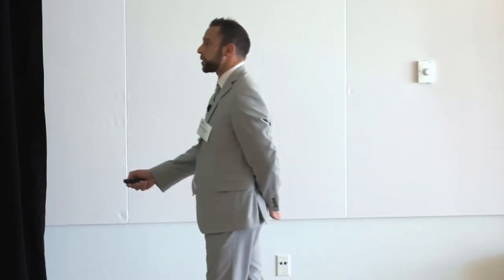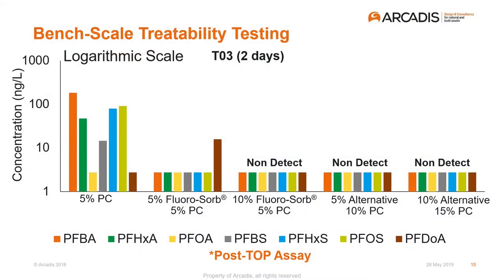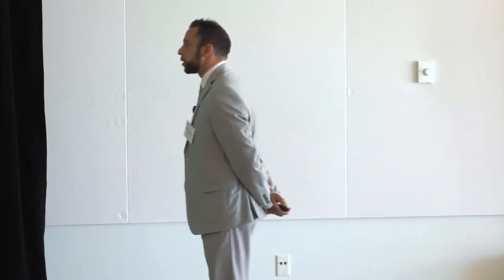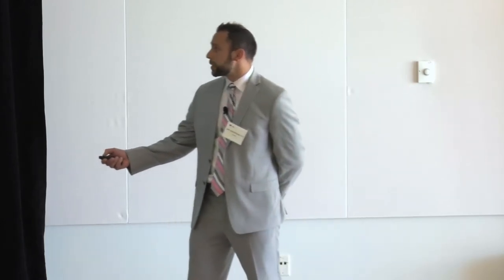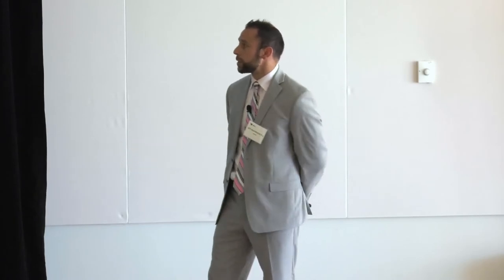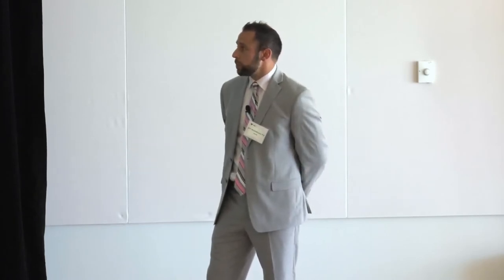Populating the data, the 5% PC, much like what Shadi saw, didn't do very much. All the others, for the majority, were non-detect. This one C12 carboxylic was right around 13 parts per trillion. Could have been matrix interference, could have been an anomaly, could have been a precursor transformation. This is all post-TOP data, but certainly was not present at the 10%, neither at the 5% or 10% of the alternative. So the data is what it is, but what we keep in mind is that this is still close to two orders of magnitude reduction in leachate for a source zone management strategy.